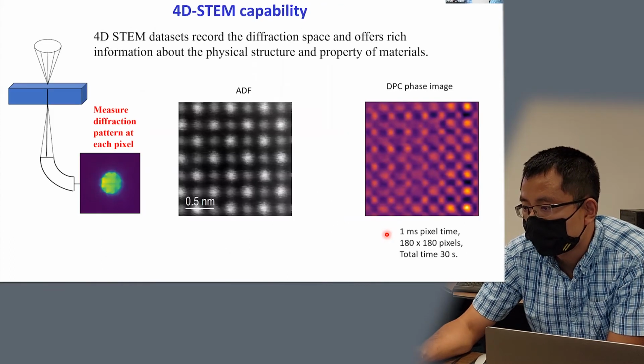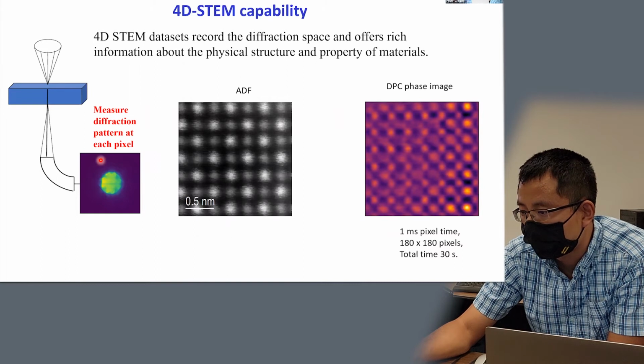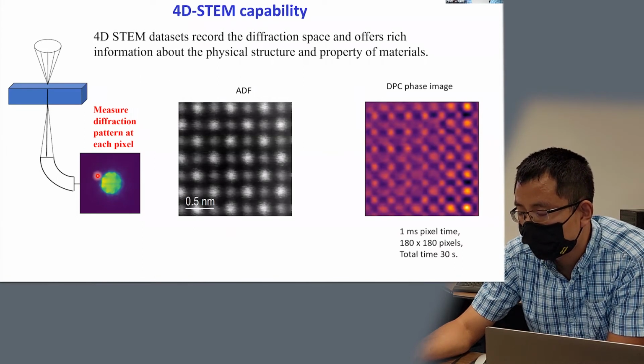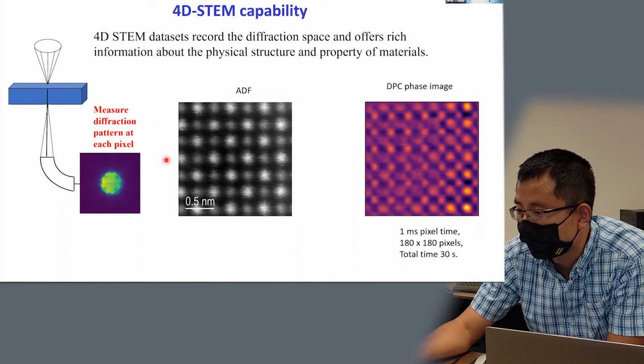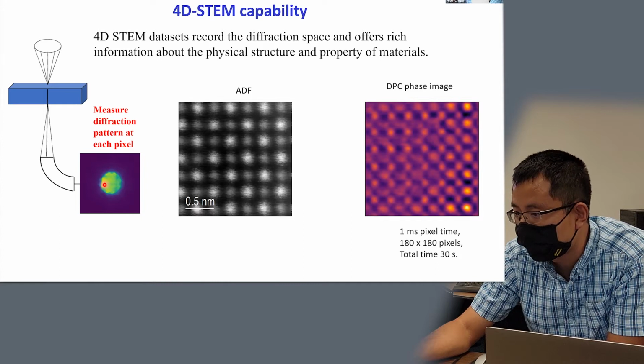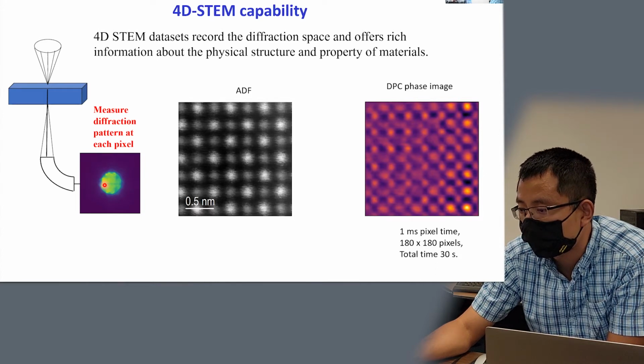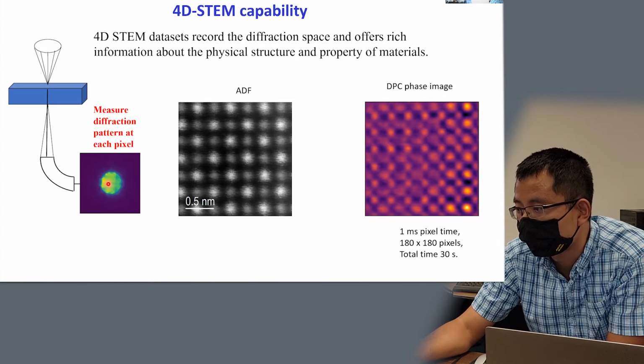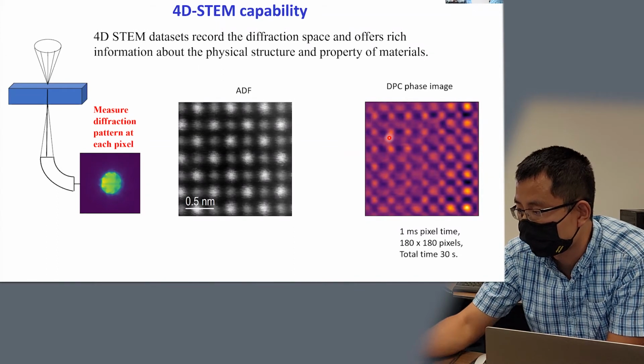And then with the new detector, we can also collect the diffraction pattern at each pixel from the material. This image shows a normal annular dark field image. And while scanning to collect the image, we can record the diffraction pattern, which is shown here, at each pixel. And then we can reconstruct useful information from the diffraction pattern. For example, this image to the right shows the reconstructed phase image, which can be used to show very high spatial resolution and contrast related to the atomic structures.